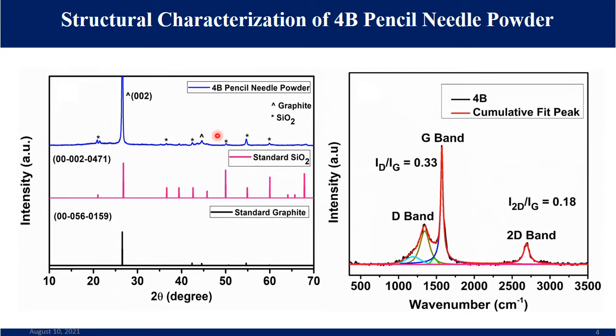In the Raman spectroscopy, the two major peaks around 1350 and 1580 per centimeter correspond to the D band and G band respectively. The D band arises from the A1g radial mode of vibration, whereas the G band arises from E2g in-plane crystalline vibrations. The peak intensity ratio, that is D band to G band, measures the defects or disorderliness in the carbon materials. The ID/IG ratio of 4B pencil needle is 0.33, which suggests that it is highly graphitic in nature. And then further, we have tested this for the pencil needle powder coated electrode.